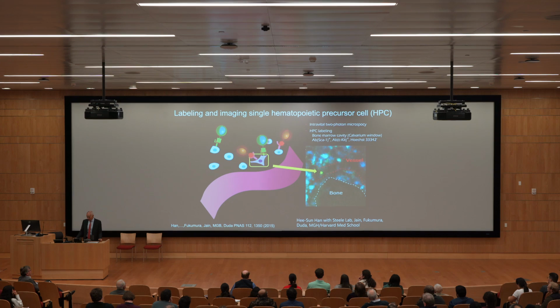Then we thought, maybe there's some easier things we can do in biology with this. One of the things that was easier was to realize that we can make quantum dots that emit in the near infrared or the short wave infrared, beyond the silicon. You can see in the 1 to 2 micron range. The advantage of going to that wavelength range was twofold. One was that there's a lot less scattering. The longer the wavelength of the light, the less scattering you have, so you can penetrate deeper in tissue.